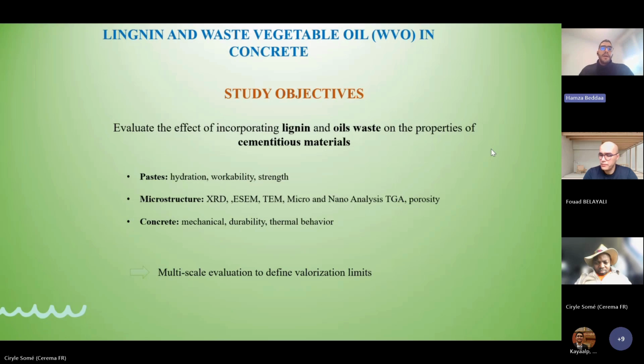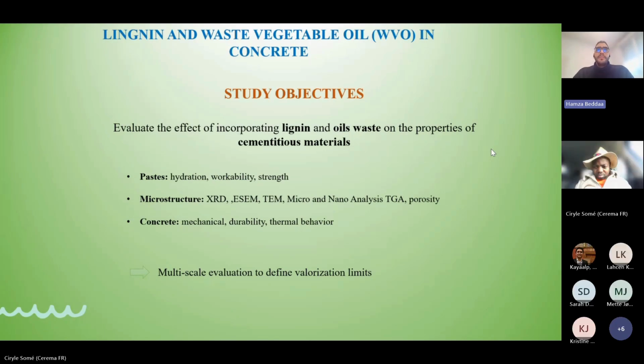The first axis is about investigating the impact of lignin and waste vegetable oils on the hydration, workability, and compressive strength of the cement paste. The second axis is about looking further and doing more in-depth investigation in order to understand the effects on these properties by doing some microstructural analysis like XRD, TGA, and also evaluating the porosity of the cement paste, in order to see the link between the effects on the hydration and the mechanical performances.